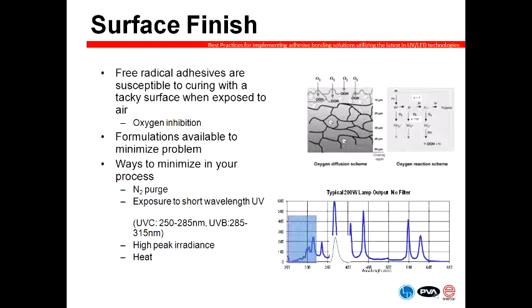Now, one of the things to consider, though, again, with the curing process is the surface finish. And this is one of the areas that comes up a lot when people are looking at using LED technology. And that is with a number of different adhesives and coatings, particularly the free radical adhesives and coatings. They're susceptible to what's called oxygen inhibition. And what that is, even though you may cure the formulation, you end up with a tacky surface. And there are ways that you can improve upon this situation. There are specific adhesive and coating formulations that are available to minimize the problem. And Frank talked about some of these with a secondary cure mechanism, such as a moisture cure. So you have different formulations available to improve this.